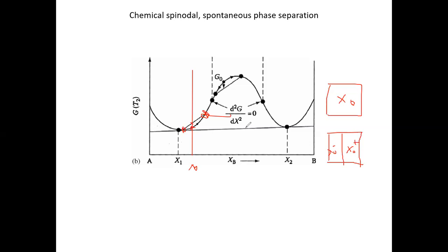It looks like it increases. It increased the free energy, right? At least it looks like it increased the free energy. And you might think, okay, this is strange. How about if we keep going and see if the separation continues, whether this is also the case? If you do that, you will see that at least for a wide range of the initial stage of separation, if you want this to proceed, you're always going to increase the free energy.